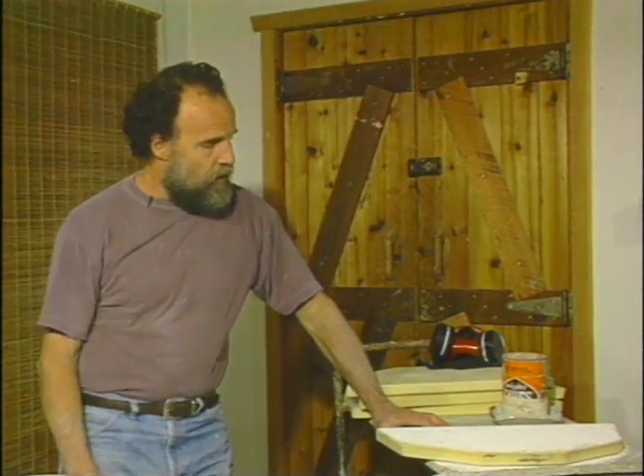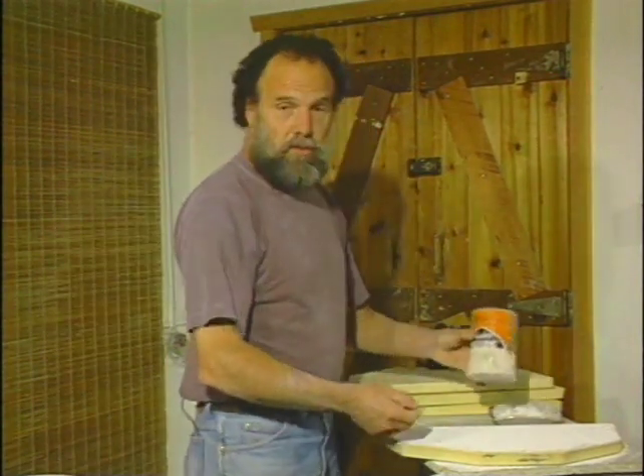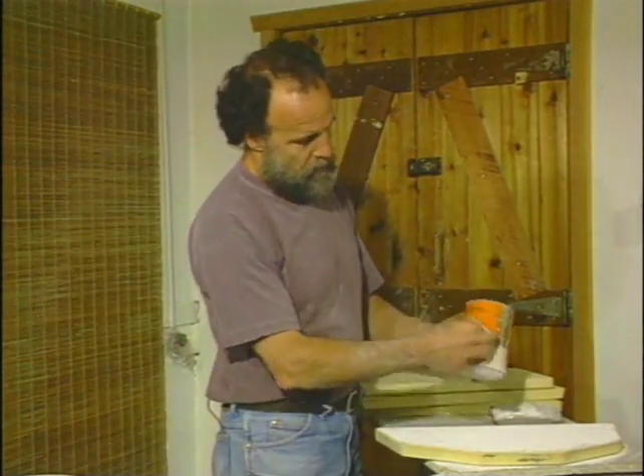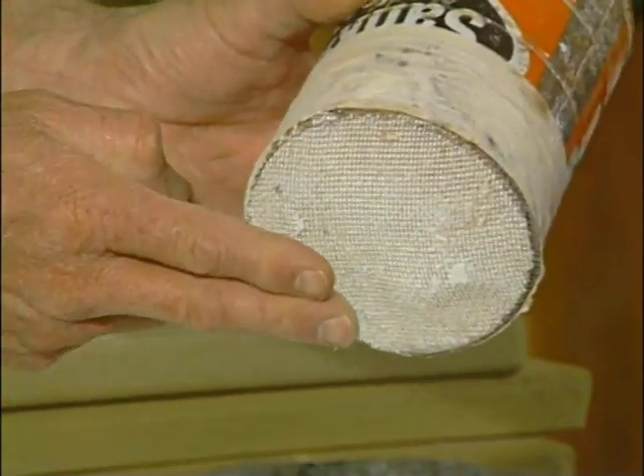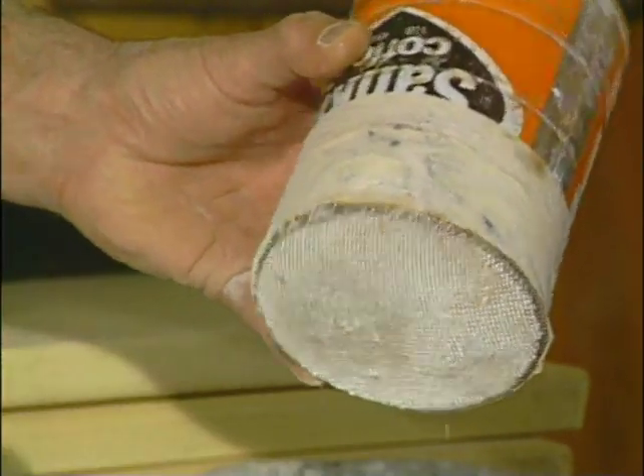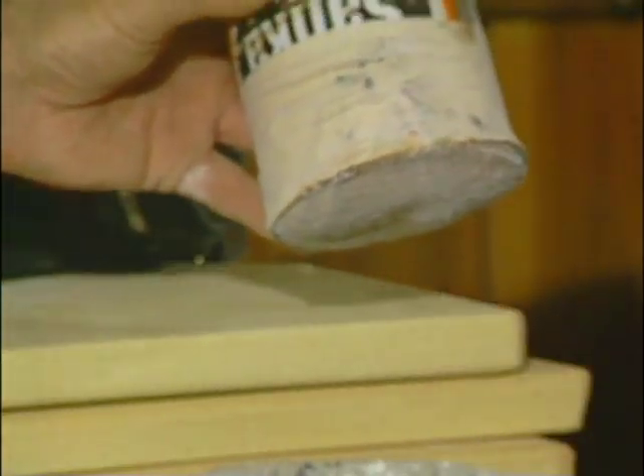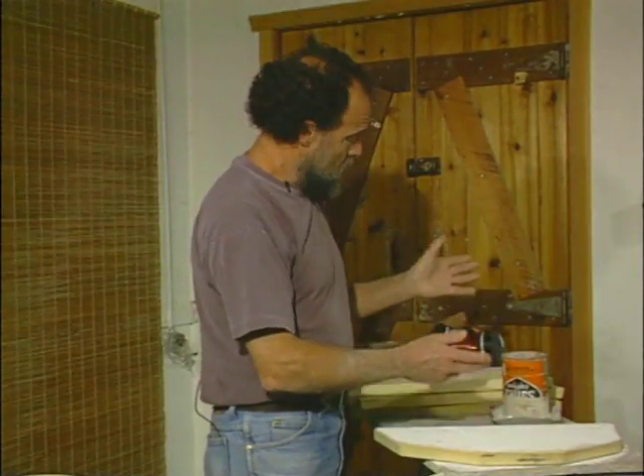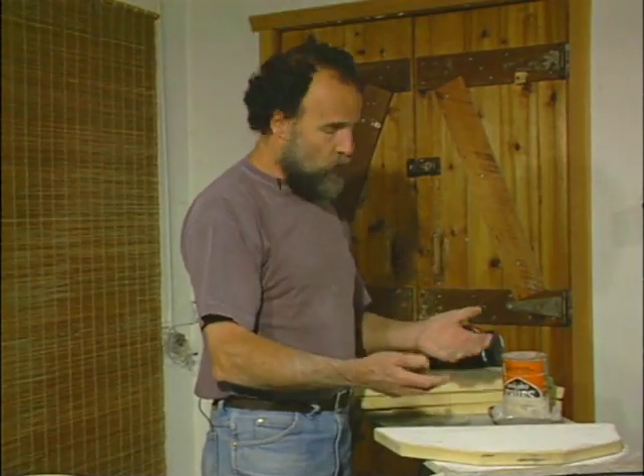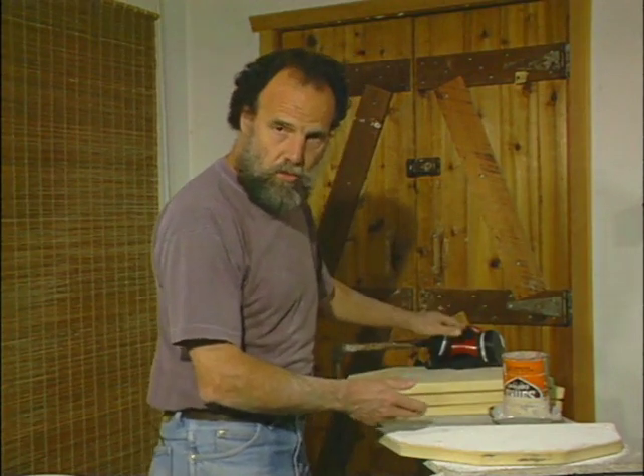In preparation for loading the glaze kiln, I've been dusting the shelves. I've been using a fine silica flour and applying it with this device here I've made out of a coffee can, the end cut out, piece of window screen on and taped. Of course, you've got to watch out. Powdered silica, the same cautions apply as when we were mixing glazes, and use your mask.